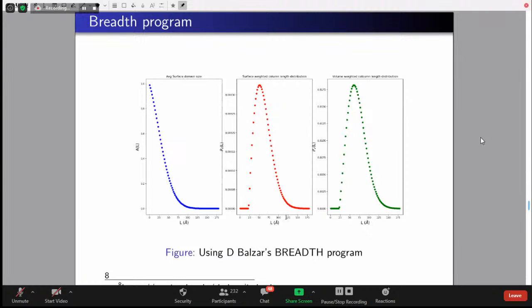So how we can formulate them is we have to bifurcate. The Williamson-Hall method will not be able to do this, but we can do it with the Warren-Averbach method, which is based on integral breadths, which can separate out the contribution from the strain and the contribution from the crystallite sizes. When it is separating out the strain values, it will show you how much is coming from the dislocations, how much is coming from the faults.